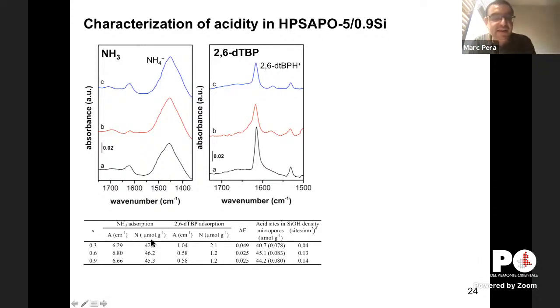What we see very clearly is that here in this table, the values of ammonia, the sites titrated by ammonia are much higher than the sites titrated by this pyridine, which means that most of our sites are located in the micropores, not outside the micropores.